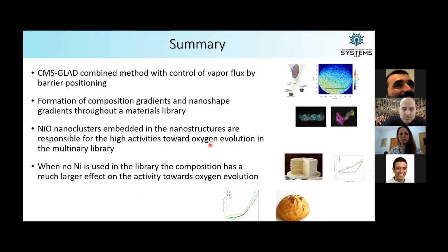And with that, I would like to summarize. I hope I convinced you that this combination between glancing angle deposition and combinatorial material science is a really interesting way to form different gradients in composition and nanoshape. And then we were able to see that the nickel oxide actually forms tiny clusters, which are much more active towards oxygen evolution. But we do also have a compositional effect as well as a structural effect. So just changing one component, in this case nickel, led us from having a very beautiful cake to having bread, or whatever you want to call it, in comparison to what we looked at before.